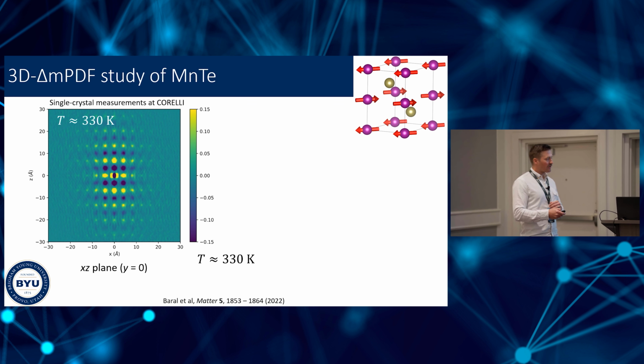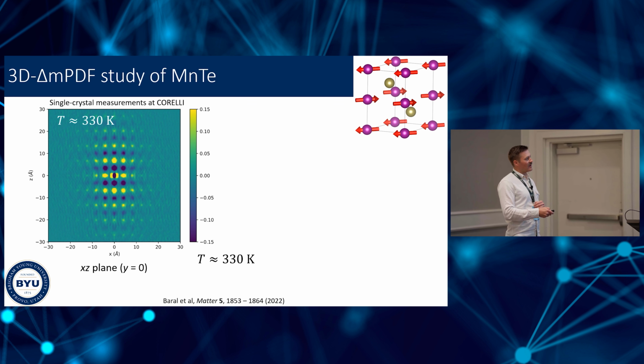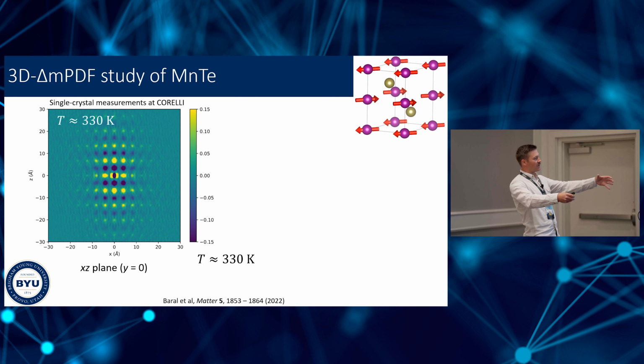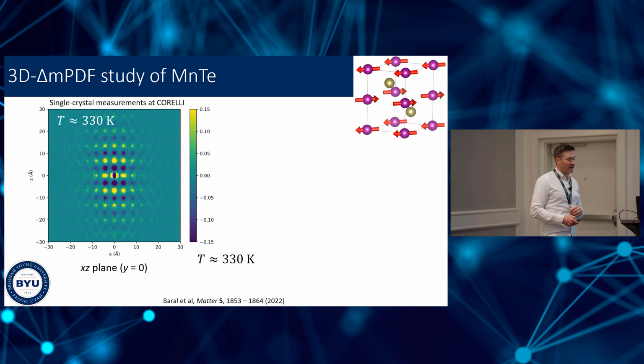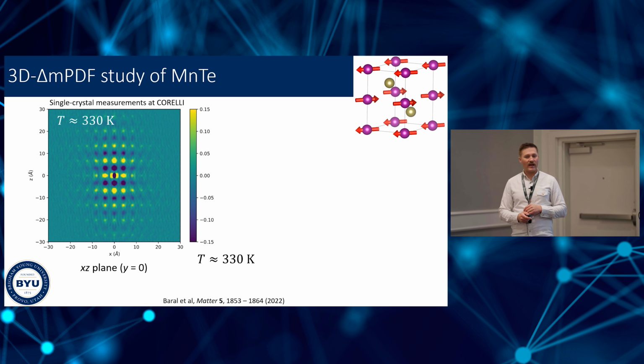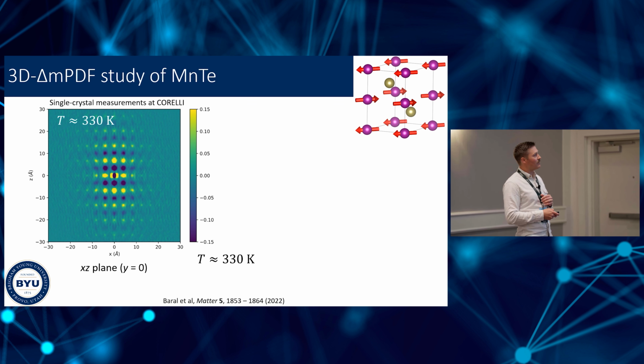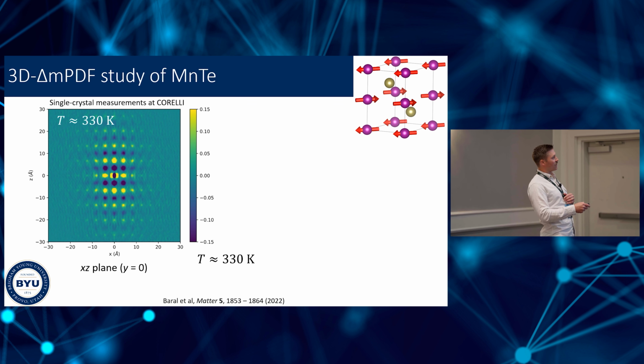By the way, if you're skeptical that we could really pull out a meaningful difference between a correlation length along the c-axis versus in the AB plane, we also did 3-dimensional magnetic PDF analysis on a single crystal of manganese telluride. This right here is a real space view of the local magnetic correlations in manganese telluride at 330 Kelvin.